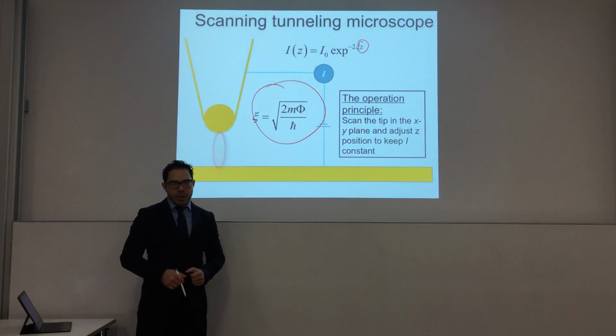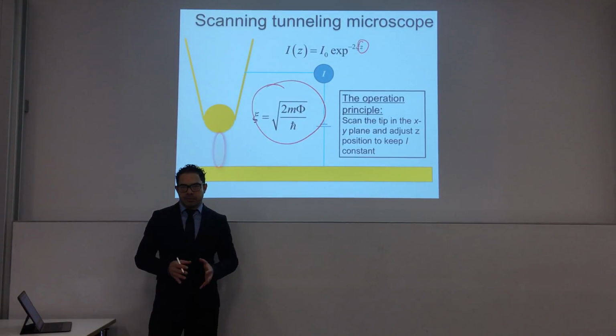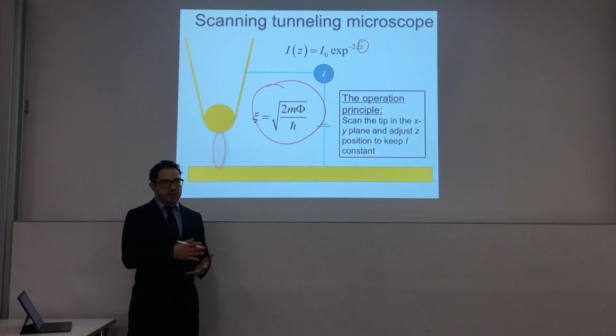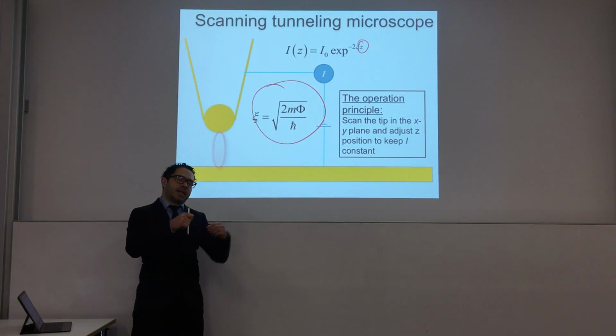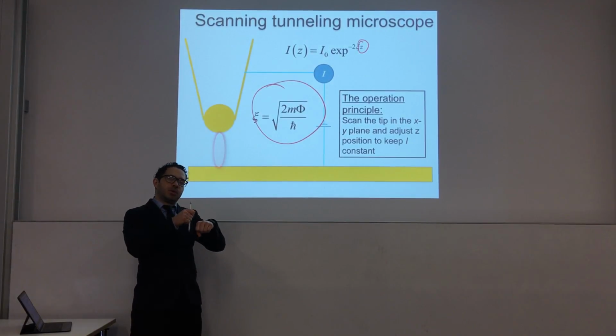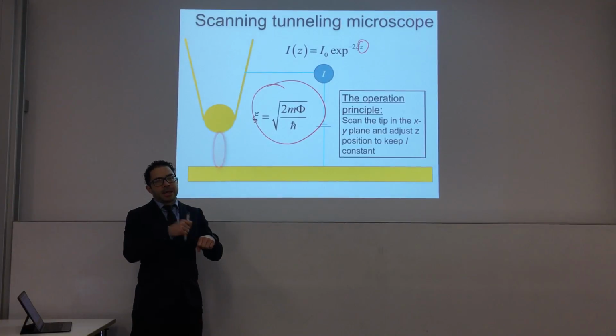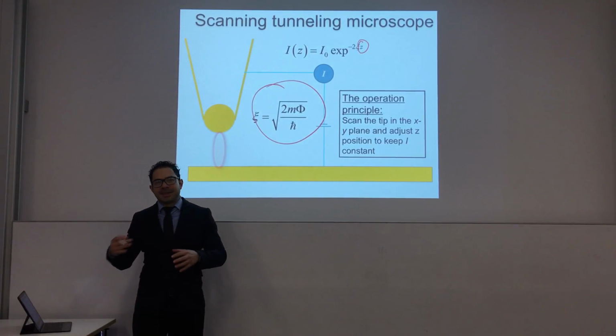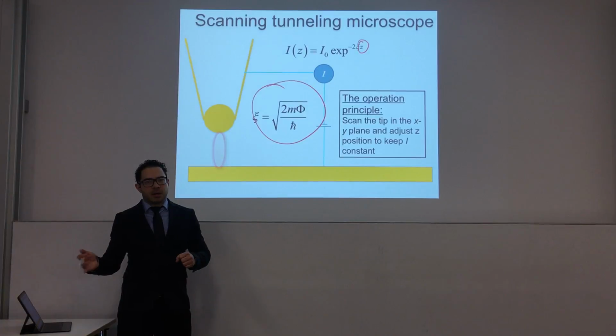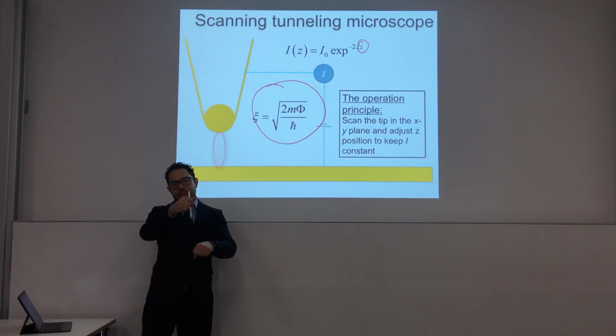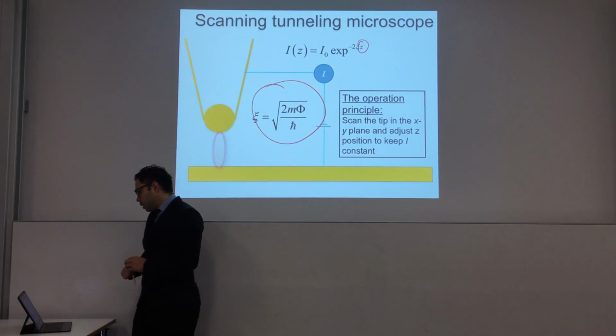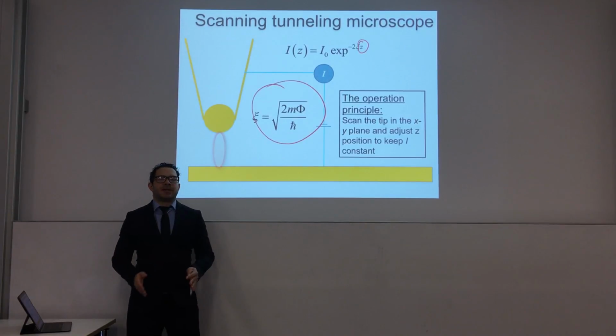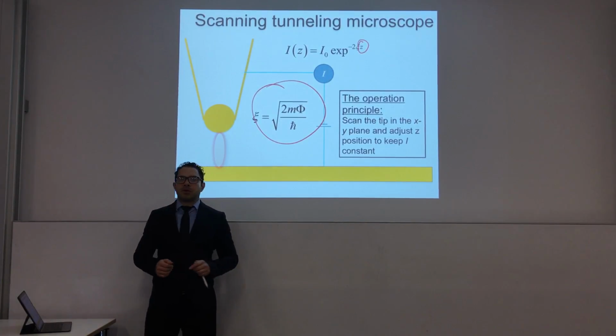Contrary, if you have, let's say, an aggregate of metal atoms on a surface, when the tip hits those aggregates, the tip-sample distance will be much smaller, then the current will increase, and the system will react to this increasing current by pulling the tip up, or the sample down. So this is basically the same principle as almost any scanning probe microscopy works.